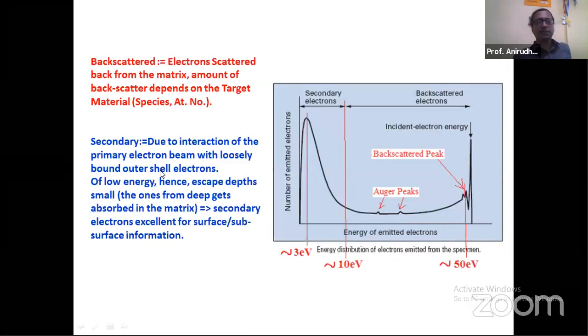Due to interaction of the primary electron beam with loosely bound outer shell electrons belonging to the matrix material, I have not written it there, they are of low energy. Since they are of low energy, those secondary electrons which manage to escape from this matrix should definitely be from very low depths from the surface, because they are of very low energy.